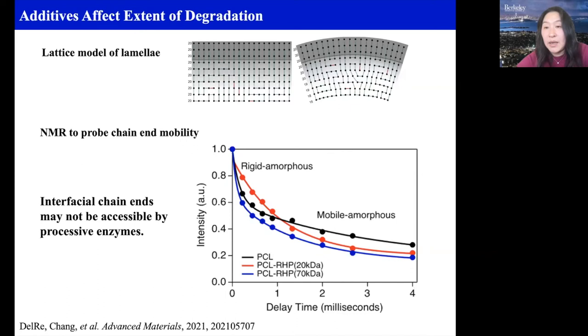So the enzyme is going to grab onto the chain end that's available and finish it. And then it cannot find another chain end available to grab onto. And basically that's how the degradation ends up stopped. And this is consistent with what we see in solid state NMR. We're basically using that to probe the dynamics of the polymer chain end. And you can see as we increase the additives, the amorphous region becomes much more rigid.